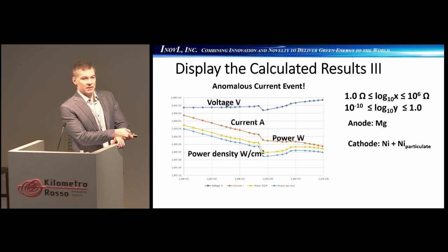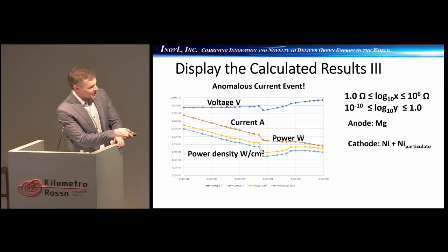And initially, when we started testing the cell, it was a very puny cell. It was not very active, didn't work very well, struggled to get down even to under 100 ohm in resistance. Just did not work until it did. All of a sudden, it kicked off. And as you can see here, all of a sudden, something happened.